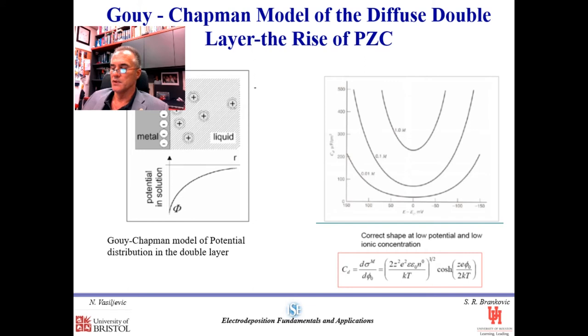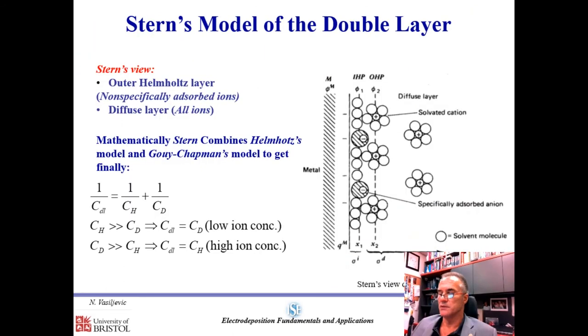There's not much organization there. That's the Gouy-Chapman model, and it describes the differential capacity of the surface as a function of the potential with respect to the potential of zero charge, which I'm going to mention in a moment, and the concentration of the ions in the solution. The important thing here is that this model defines the existence of the potential of zero charge, or EPZC. At that potential, we assume that the capacity of the electrode has its minimum. This can be understood as the maximum disorder at the electrified interface, where the probability of the positive or negative side of the dipole facing the electrode surface is about the same. For that reason, the capacity is minimal.